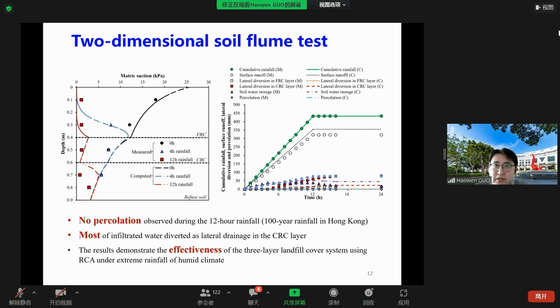And from the right-hand figure, we can find that during the initial stage of the rainfall, that means 0 to 6 hours, surface runoff and soil water storage increase linearly as the rainfall continues. But the amount of water storage reached its maximum value at 6 hours. So after that, the infiltrated water started to divert laterally in the top FRC layer and the middle CRC layer. This means that the top two layers can function as the drainage layer effectively. During the whole test, no percolation was observed, even without using a geomembrane.